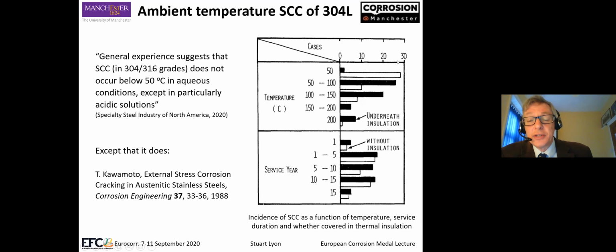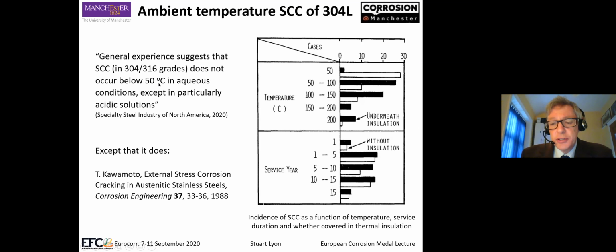This is below 50 degrees, and we can see underneath insulation, we do get stress corrosion cracking, but we get stress corrosion cracking even in the absence of insulation in a service environment where the temperature is well below this 50-degree limit. The question is why that is.